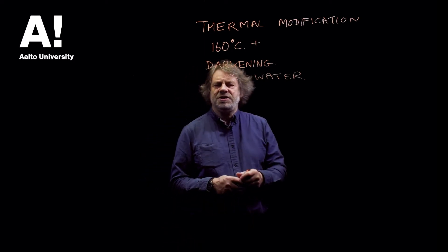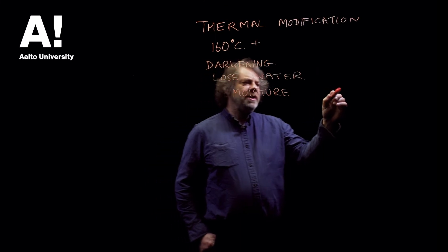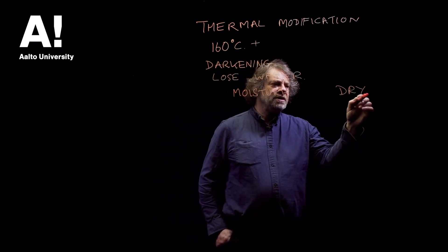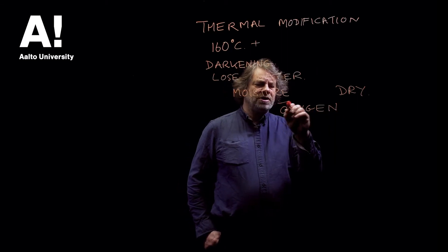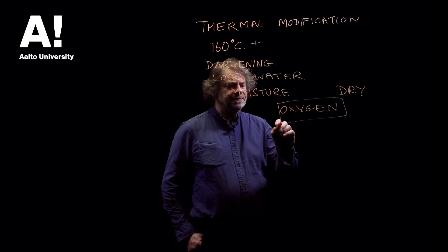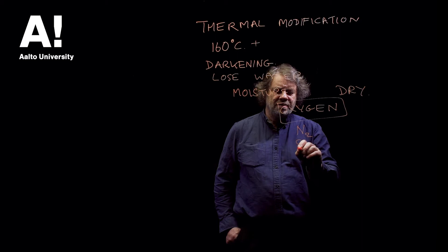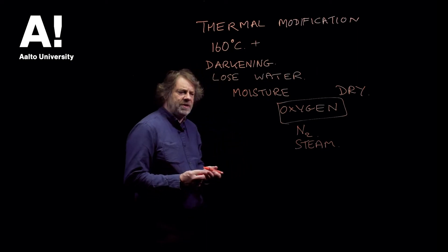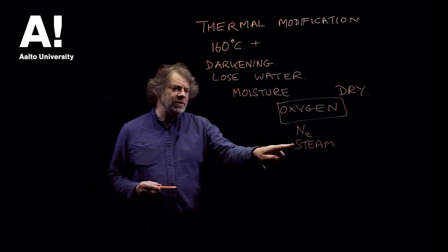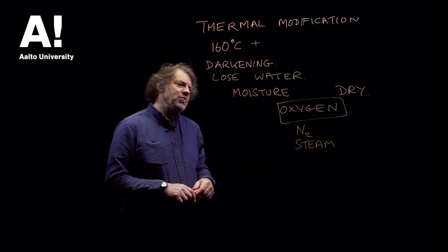The type of degradation that will occur depends very much on whether it's going to be in the presence of moisture or whether it's going to be a dry degradation, and it depends whether there's oxygen present or not. So in a thermal modification, oxygen is removed either by using a nitrogen blanket or a steam blanket — those are the usual ways of doing it. You get different types of reactions occurring depending on whether there's moisture present or whether it's done in a dry environment, and there are pros and cons behind each one.